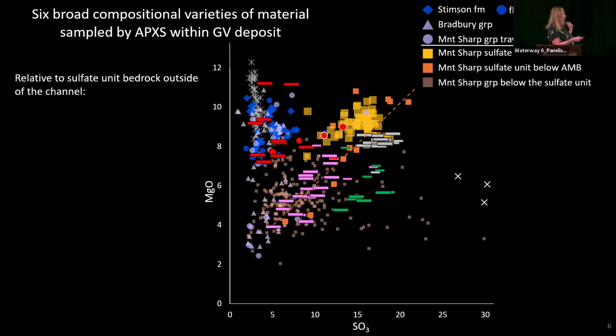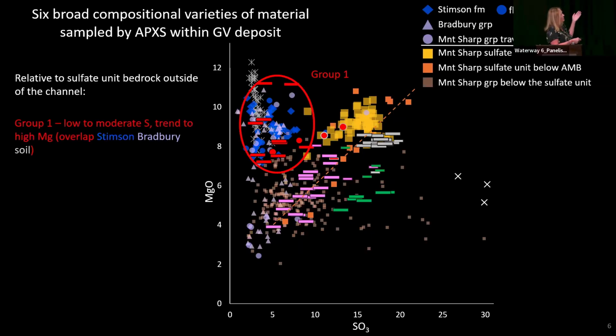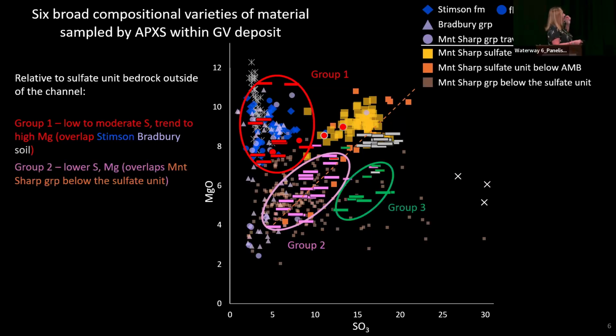And again, we're just seeing the groups on this plot of MgO versus SO3. So again, group 1 is overlapping the Stimson Formation and the Bradbury group and soils. Group 2, again, is overlapping the sulfate unit below, the Mount Sharp group below the sulfate unit. And group 3, you can see, although it has the same sulfur and calcium as the bedrock outside the channel, the magnesium is significantly lower.